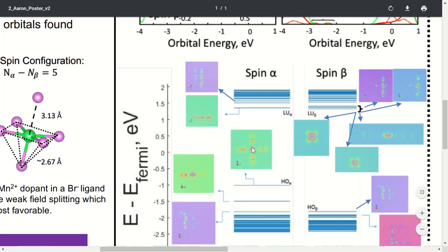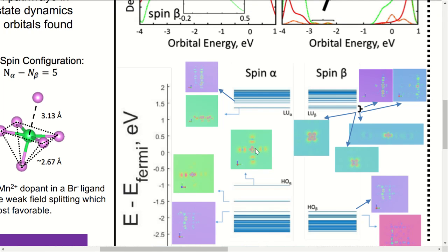So this is with the spin polarized basis. When you include spin orbit coupling, they become more orthogonal to each other. Because that's one problem with GGA functionals: your orbitals tend to over-delocalize. So spin orbit coupling, you can think about it in some ways as including exchange correlation effects too, to correct the orbitals.